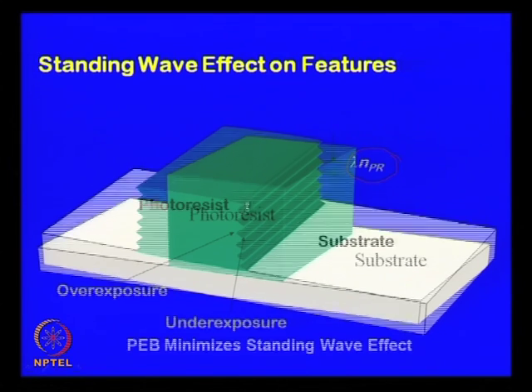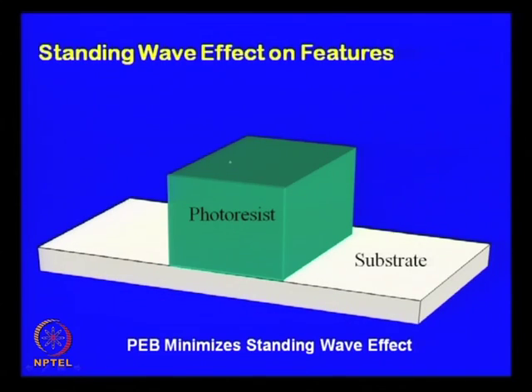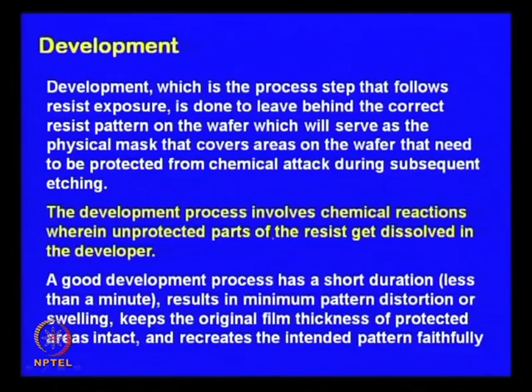Your post exposure bake actually takes care of the standing wave effect, and because of this annealing it minimizes the standing wave type of structure. So, once post exposure bake is done, the next stage, the final stage I would say, is the development, which is the process step that follows. The resist exposure is done, and development leaves behind the correct resist pattern.